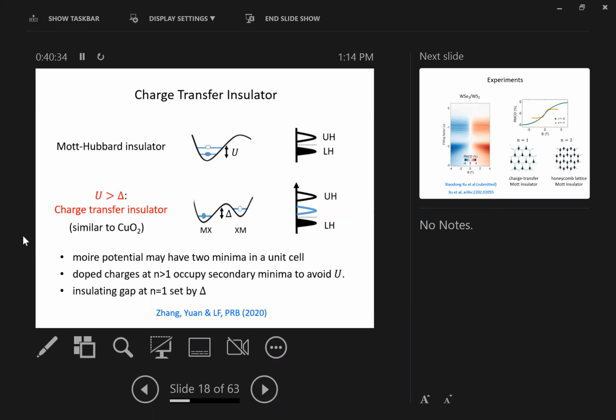On the other hand, we proposed from early on, almost 3 years ago, that there could be an alternative possibility. Based on our DFT calculations, in many TMD heterostructures, including this WS2/WSe2, we found that the Moiré potential has multiple minima within one unit cell. There's a primary energy minimum in one type of local stacking region, and there's a secondary potential minimum in another local stacking region, this MX and XM region. And the energy difference between these two potential minima, which we call delta, is small. It's on the order of a few tens of millielectron volts. It's small compared to the Hubbard U.